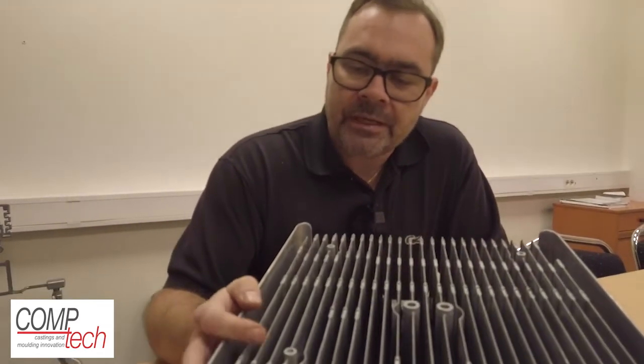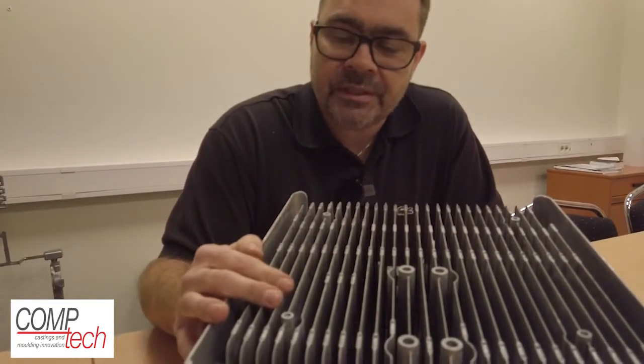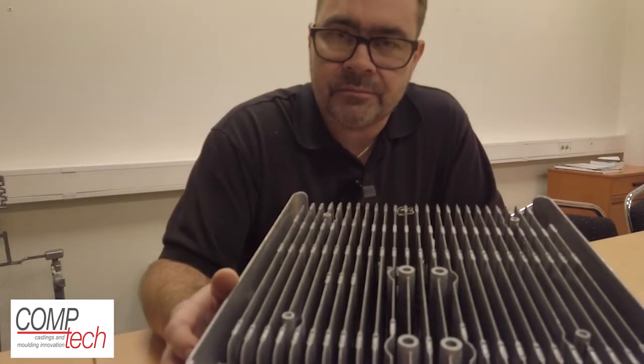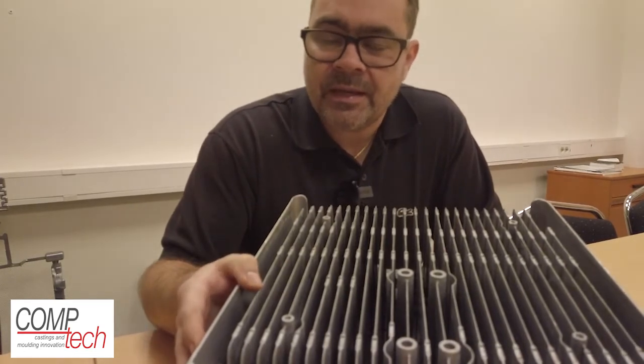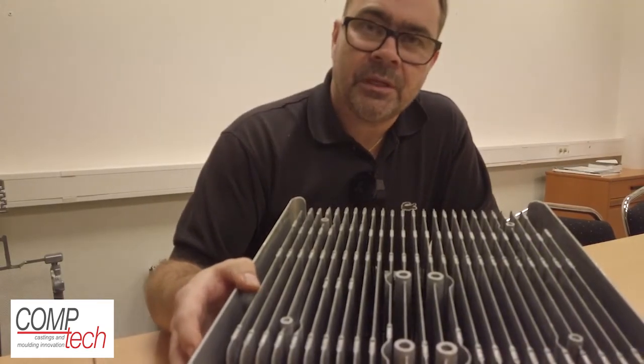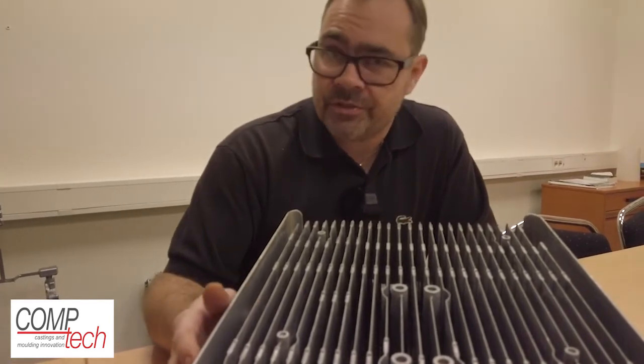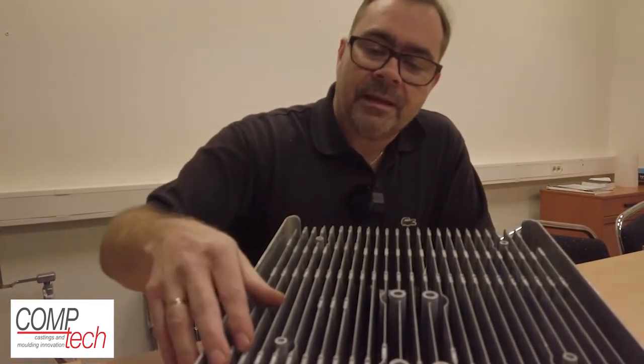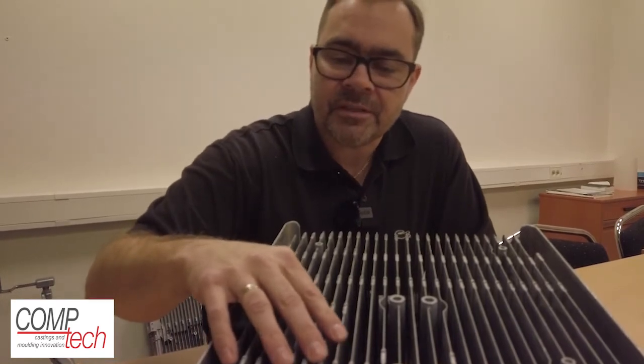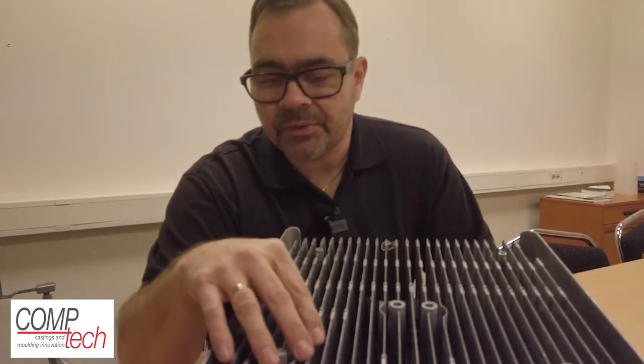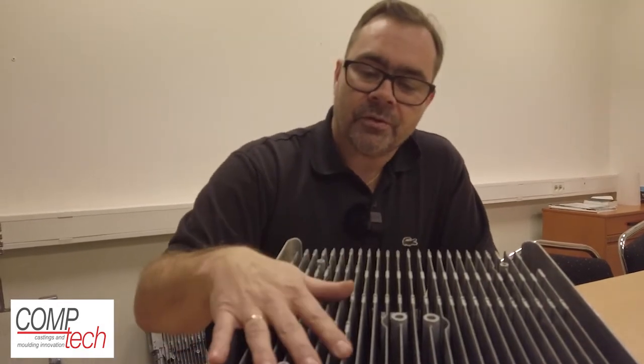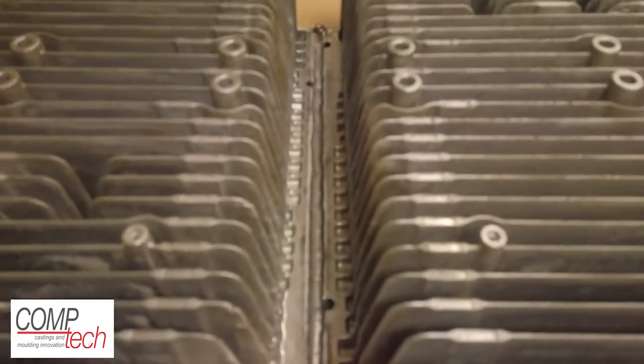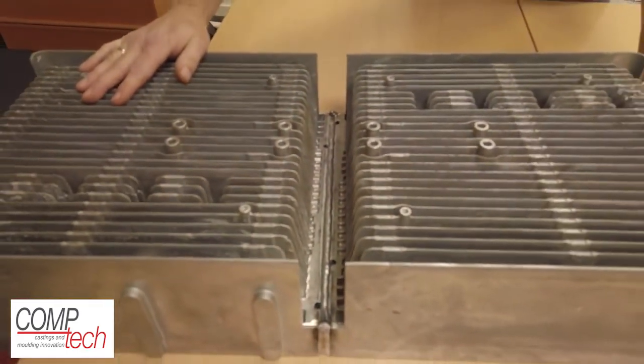Another application where Rheocasting have proven its abilities is within heat sinks. Here we are able to cast very complex geometries in an alloy with only 3% silicon. That allows us to enhance the heat conductivity up to 180 watts per meter Kelvin in as cast state. And 105 millimeter high fins with a draft angle of 0.6 degrees per side, also casted in an 800 ton machine. The requirement for heat sinks are that they are growing and growing as well.